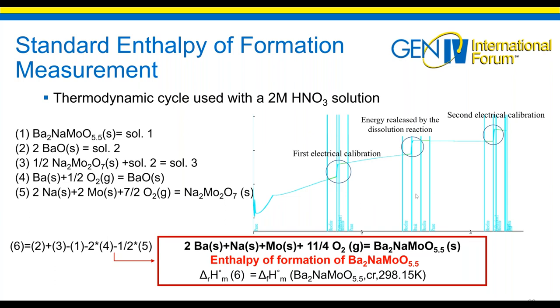So then you have the energy released of one reaction, and then you can perform a thermodynamic cycle using just basic math to obtain this reaction, which is called the reaction of formation of the quaternary compounds, and this enthalpy will be the enthalpy of formation of your compound. But of course, to get this, you have to measure the enthalpy of reaction of all your reactions, so 1, 2, 3, 4, and 5, and then you can sum them to get it in the end.